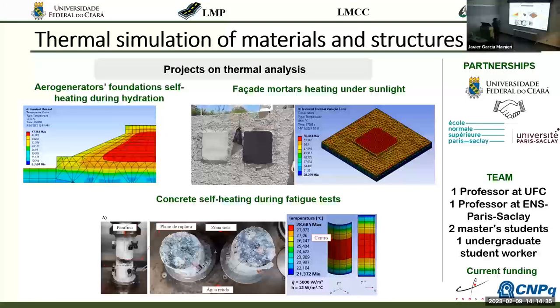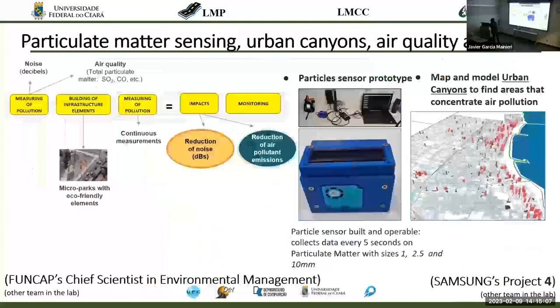If you do compressive fatigue tests in concrete, there's so much energy that you put in the material that the material gets hot. Few researchers are actually measuring how hot it can get, but it can get up to 90 degrees during the test. So you start the test at room temperature with your concrete. At the end, you're testing it at 95 degrees. And this is because there's a dissipative mechanism that gets your specimen hot, and you can calculate that as well. So we have many applications of thermal analysis. These are some of them.